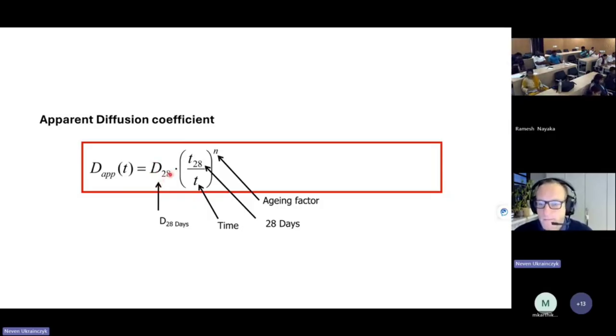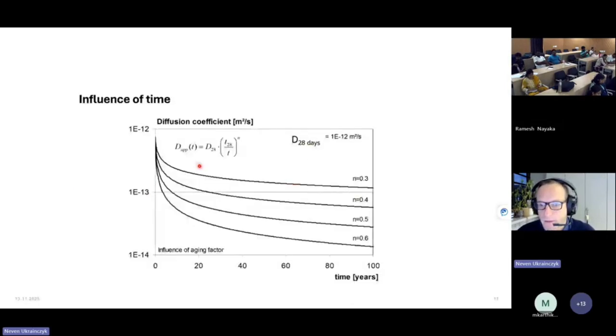hydration time. And then here is the aging factor, typically 0.3, and this is how the apparent diffusion coefficient changes with time. So this makes the diffusion coefficient also time dependent, of course, and you can see this influence of time. Typical value is 10 to the power of minus 12 meter squared per second.